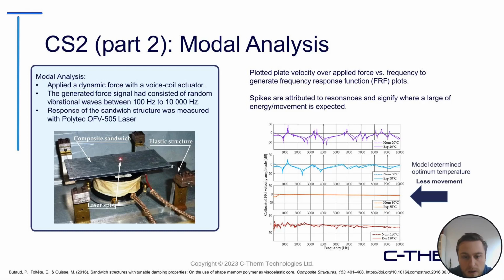So they made their sandwich structure with this viscoelastic material, which was sandwiched between two aluminum sheets, and they did modal analysis on it, where you basically apply a dynamic force to a sample and measure its response. This is huge in the automotive industry, really anything that's moving.